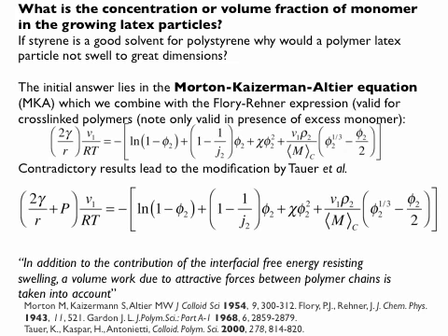And this correction term in polymer science, but also in other disciplines, is described by the Flory-Huggins theory. The Flory-Huggins theory gives you the third term in this case, which is the Flory-Huggins interaction parameter times the volume fraction of the polymer to the power 2. And the Flory-Huggins interaction parameter is a measure for how well stuff mixes.